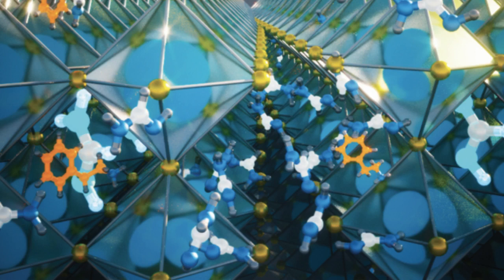The researchers learned that the surfaces of metal halide perovskite films treated with organic cations keep evolving in structure and composition under thermal stress. They saw that the resulting atomic scale changes at the interface can cause a meaningful loss in power conversion efficiency in solar cells. In addition, they found that the speed of these changes depends on the type of cations used, suggesting that stable interfaces might be within reach with adequate engineering of the molecules.